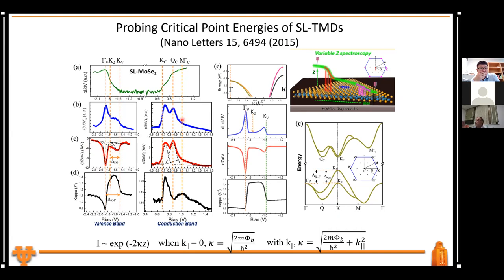Now, when you pass through the K point, you start sensing the states from the underlying graphite. So this transition is smoother, unlike the state at the gamma point, which is very sharp. Then if at the same time you measure the tunneling decay coefficient, then indeed at the gamma point, you have the smallest kappa value. And then when you go up near the K point, your kappa value will increase.